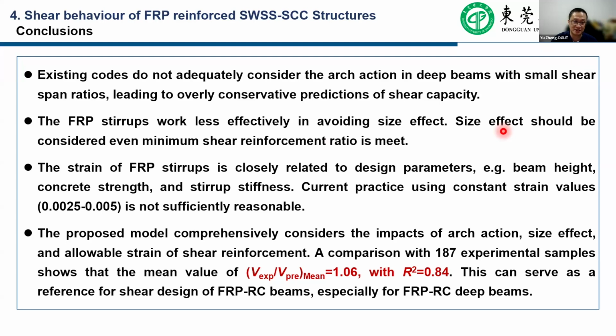The size effect still needs to be considered, even though the FRP stirrup is used for the construction. And the strain of the FRP stirrup is closely related to several structural parameters, such as the beam depth, the concrete strength, and the stirrup stiffness. And the current design standard using the constant value is not reasonable. And our proposed model shows a good correlation with the test results.